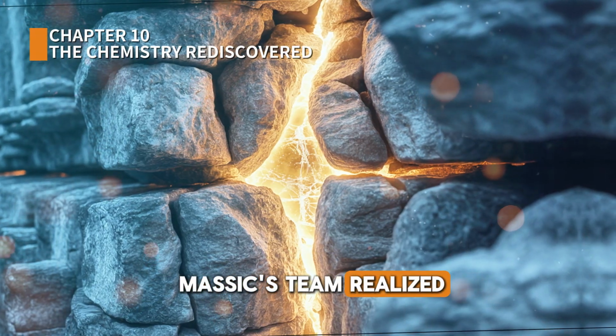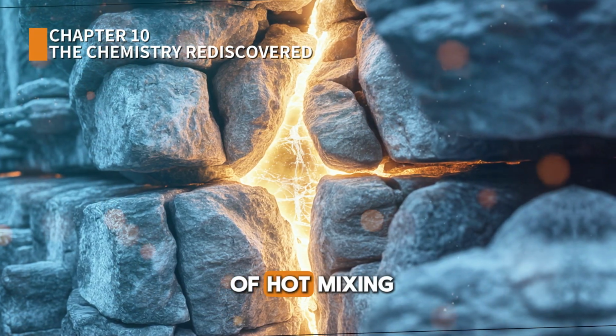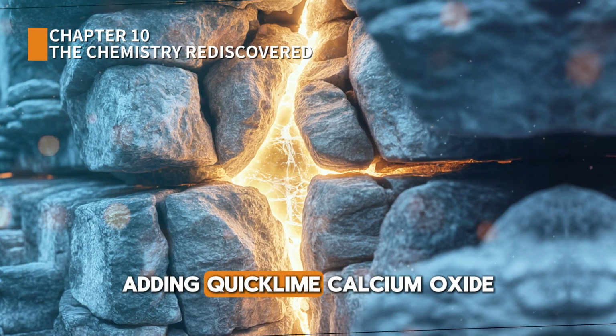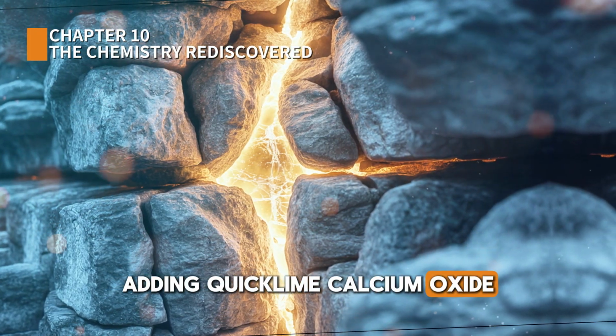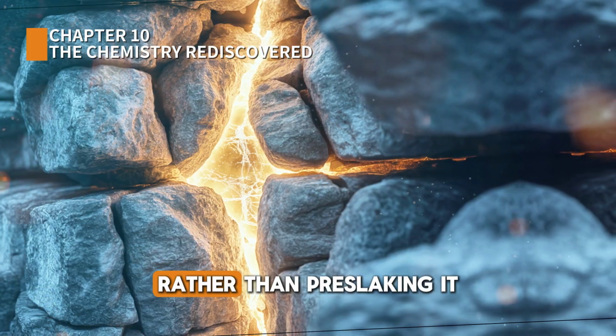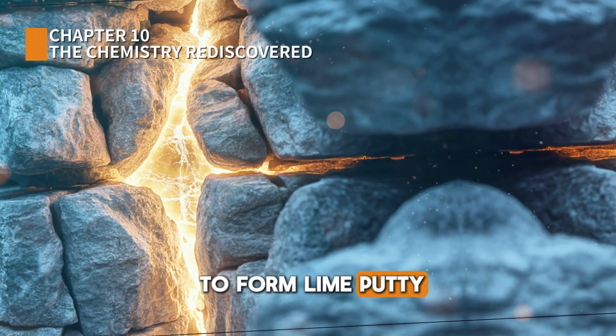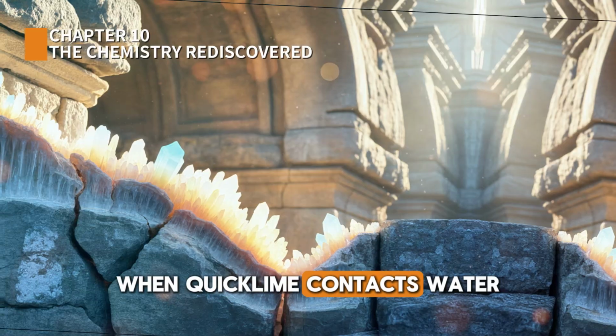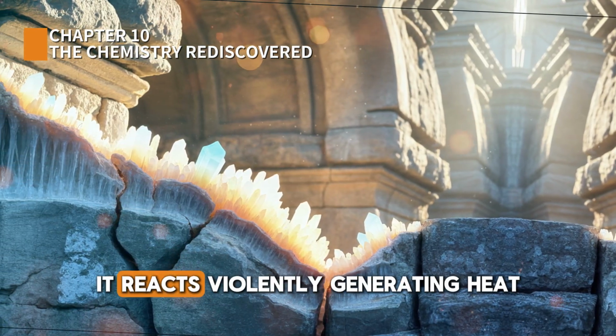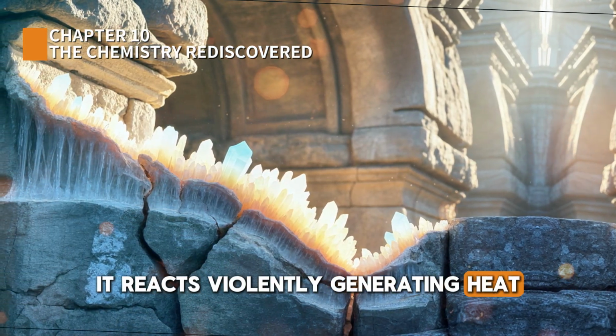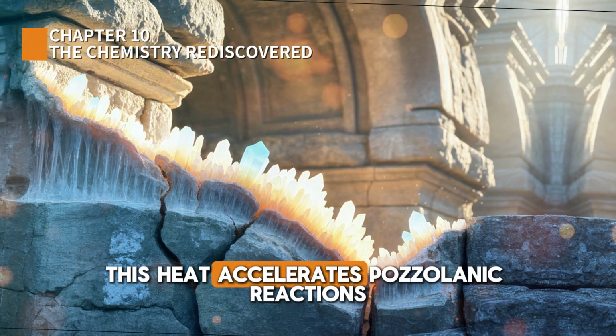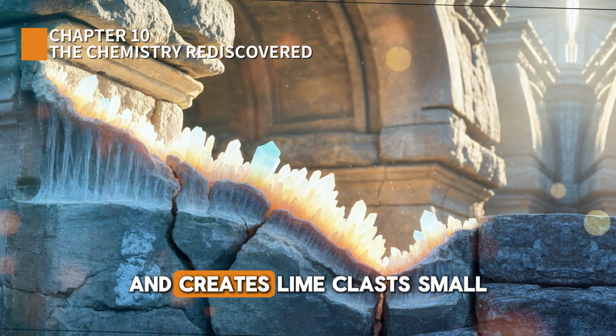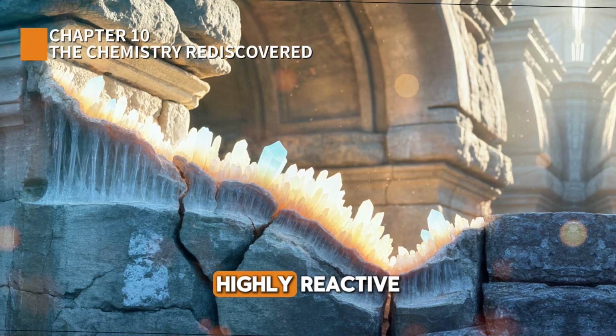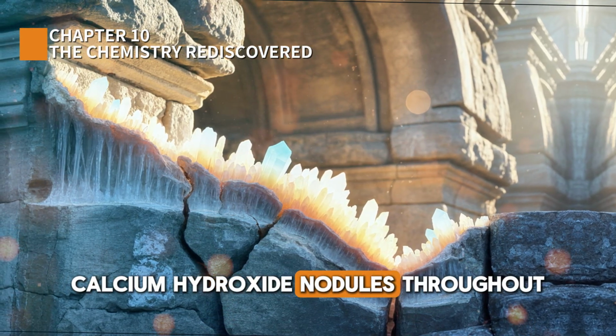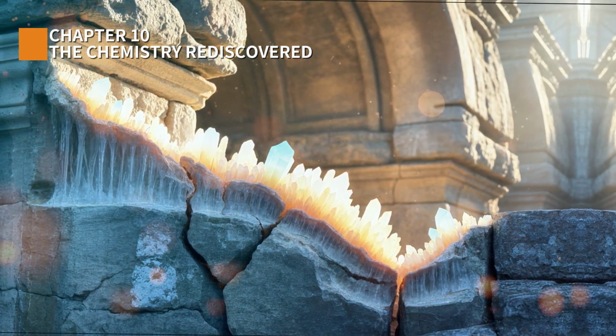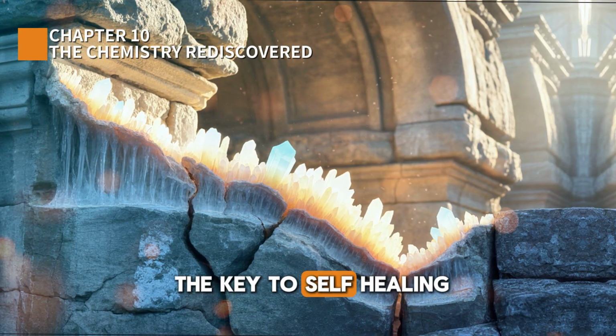Masic's team realized they were seeing evidence of hot mixing, adding quicklime, calcium oxide, directly to the mix, rather than pre-slaking it to form lime putty. When quicklime contacts water in the concrete mix, it reacts violently, generating heat. This heat accelerates pozzolanic reactions and creates lime-clasts, small, highly reactive calcium hydroxide nodules throughout the concrete. These lime-clasts are the key to self-healing.